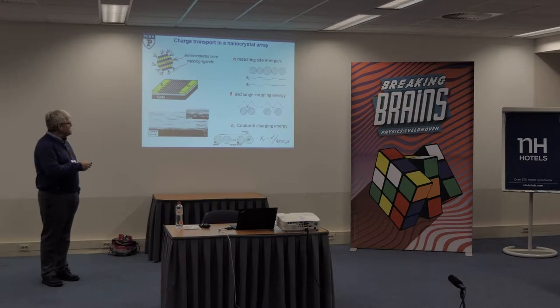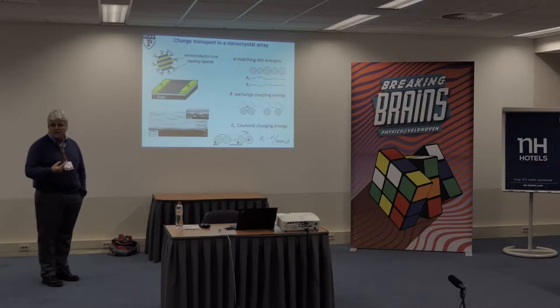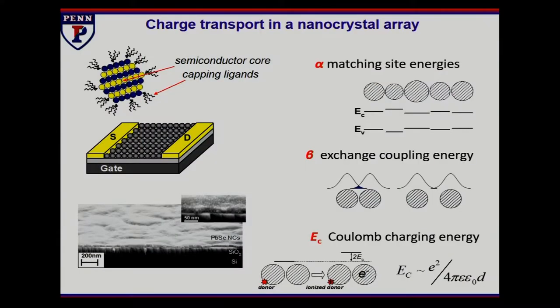paying attention to. But what it did allow us to do was to take some of these very uniform particles, begin to couple them close enough in space, and also allow the electronic density of the quantum confined wave functions to begin to overlap between neighboring particles. There are a couple of other things that help here in terms of high dielectric constant, which reduces the amount of Coulomb penalty, charging energy, that the materials have to pay as charges move through those systems.